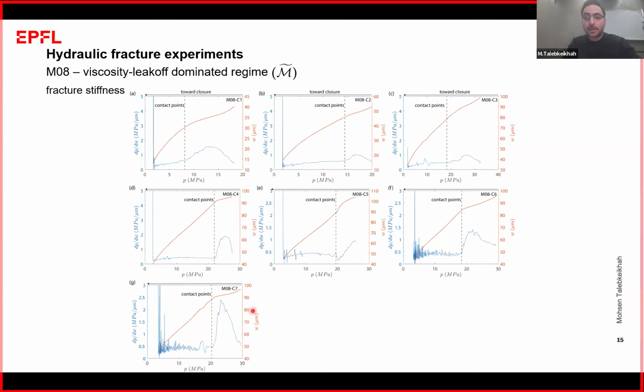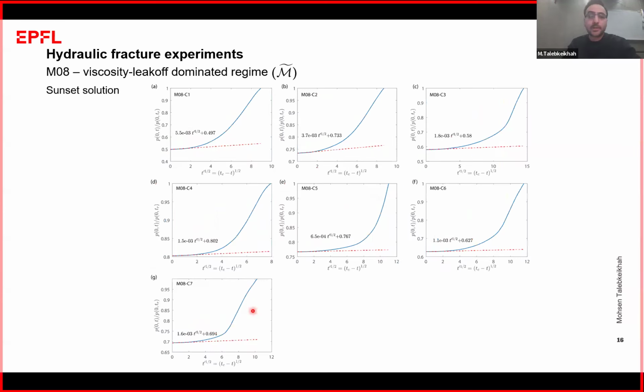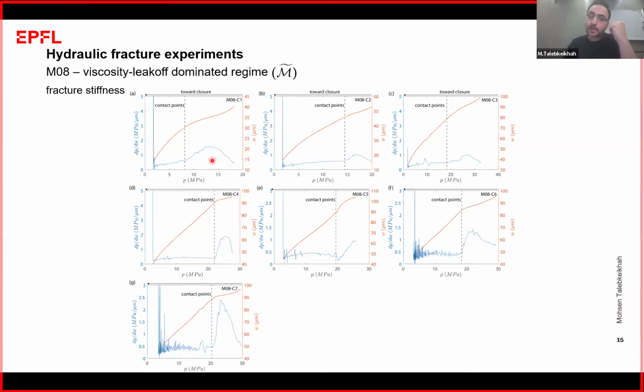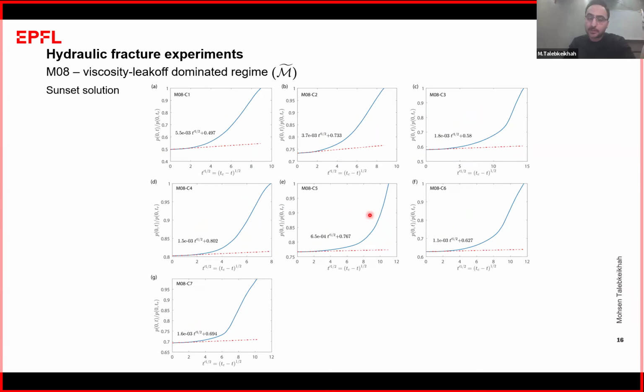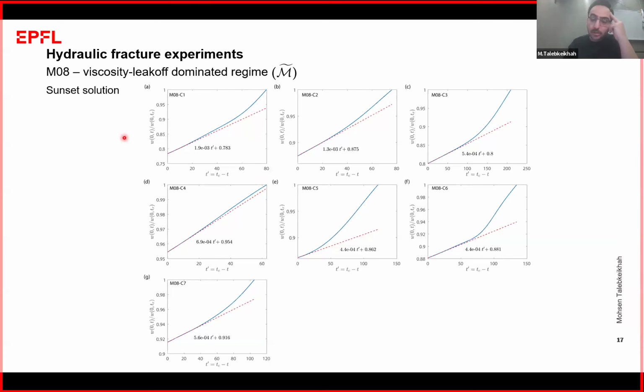So also I plotted the pressure asymptote at those peaking points for each cycle. I plotted the pressure asymptotes of the solution, and we could see the linear behavior of the pressure at the inlet with the square root of reverse time. Also for the opening asymptote, we can see the opening at the inlet has a linear relationship with the reverse time in each cycle.